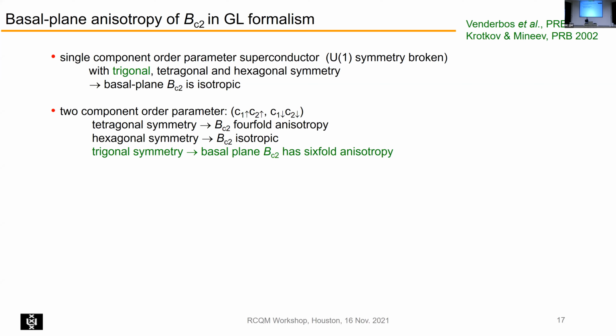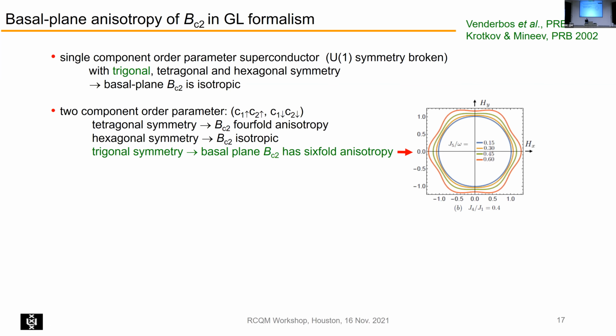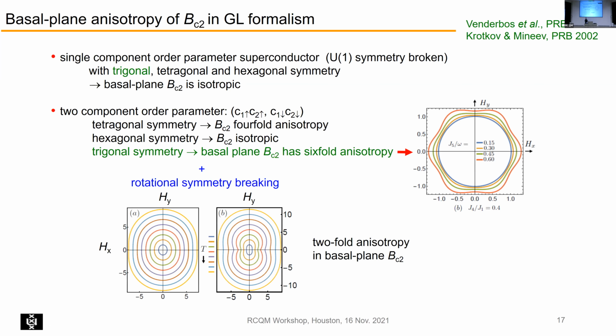But if you have a two-component order parameter, like this one, so this is like a linear combination of two equal spin pairing states, then in the tetragonal symmetry, you would get a 4-fold anisotropy. Hexagonal uranium platinum 3 still isotropic, but if you have a trigonal symmetry, then the basal plane can have 6-fold anisotropy. So it looks like this. And so then you can have an anisotropy of the upper critical field. So when you take the field in the plane, you get this. But that's not what we observe. So that's now the difficulty. What we observe is more something like this. And so it is like 2-fold.